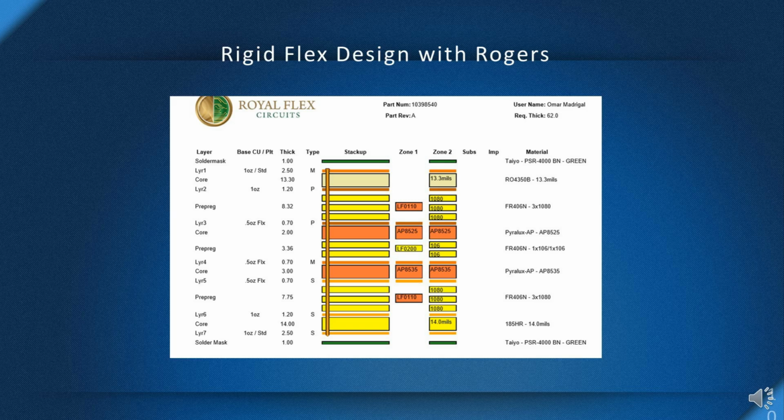I guess the next thing. Oh, were there any processing challenges that we had with this? Because it is a very delicate material. Well, the fact that we handle lots of thin flex as it is, we do as low as a 0.5 mil core thickness. So the methods we use with framing and using carriers through the process minimize any effect. It is very susceptible to folding or damaging through typical equipment, but because we run a lot of flex materials, we have the handling techniques to minimize any effects in processing. Flex and real thin cores take special handling in any shop.